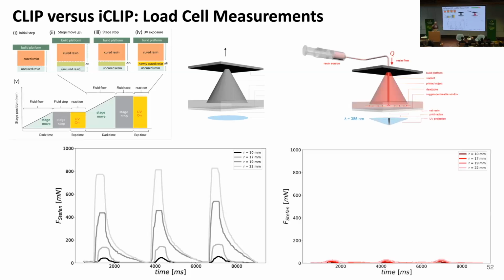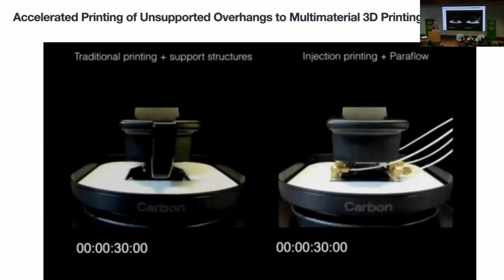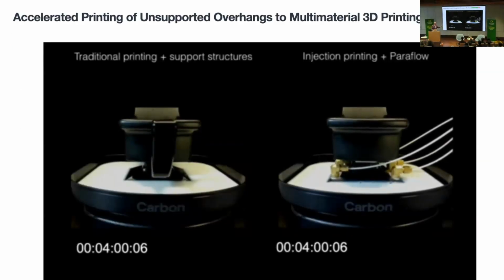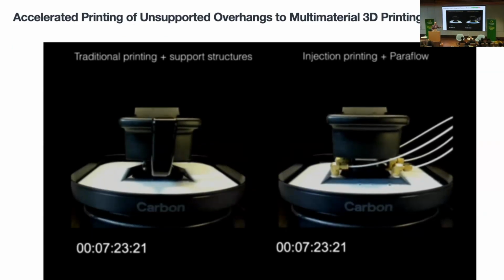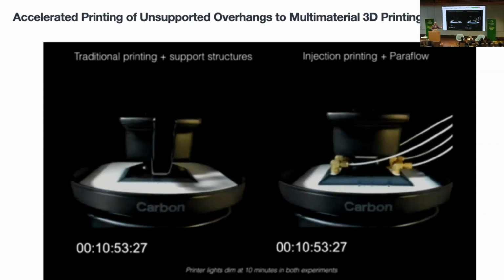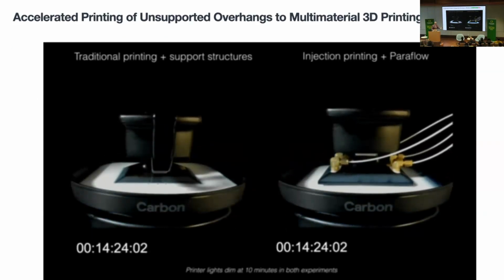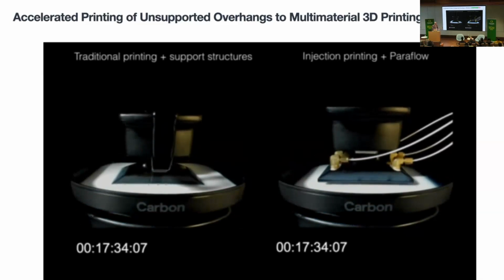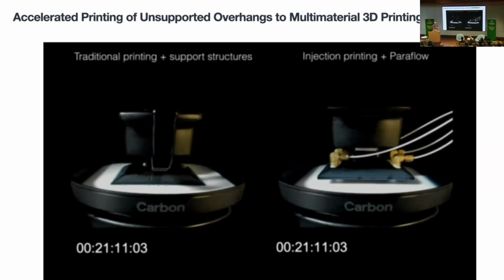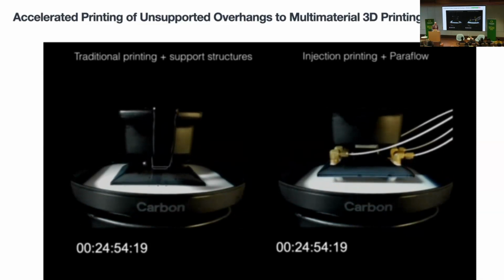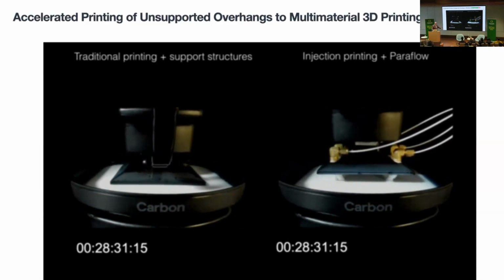When you're injecting liquid, these forces go away because you're pushing liquid into the gap. In fact, it's kind of like walking up to a wall with a fire hose. You're actually getting pushed back the other direction. So we can eliminate those forces. The printing goes an order of magnitude faster than the traditional. I already told you we're going 100 to 1,000 times faster. This is another factor of 10, using a liquid that's being injected through the platform, through the parts as we create them. So another factor of 10 on speed. I'm not going to wait for this to play through.